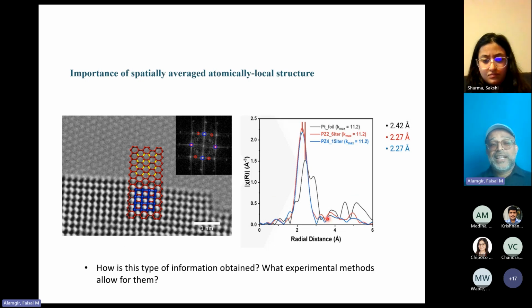And what is that? It's the so-called radial distribution function. It is the probability of finding an atom at a particular distance. So if you're able to find an atom at a particular distance, you can organize that histogram, and that histogram now tells you what is going on in your material on average. So here, particularly, we're looking at platinum on graphene. So the atom around which we're focused on is the platinum atom. And so we're looking at these peaks here, and these peaks then represent the nearest neighbor and then the second nearest neighbor around platinum and so on.